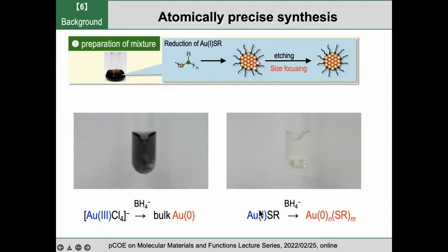But when we reduce gold-sulfur complex, in this case gold is formally 1+, after addition of sodium borohydride, the reduction takes place very rapidly, and you can see a transparent brownish color. So this is the mixture of the stable magic clusters in solution. And after adding excess amount of thiol in this solution, some metastable species are etched into small stable species. So size focusing occurs in solution. So just after this process, we have a mixture of magic clusters in solution.